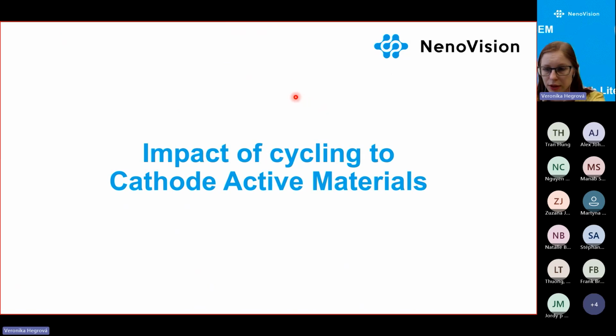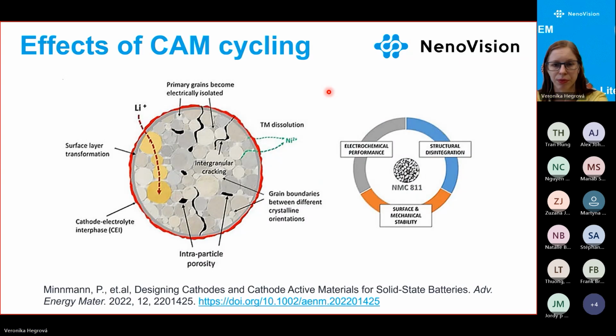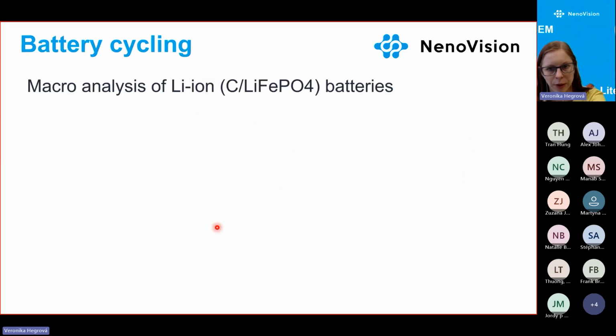Let's have a look at cycling. How is the cycling impacting the cathode active material? What is cycling actually doing to these materials? I don't want to go in depth, but what is happening during cycling, the charging and discharging, is making the grains, let's say, breathe, expand and contract. And this expansion is making cracks between the secondary grains or primary grains and creates some porosity and makes connections worse and worse with the cycling.